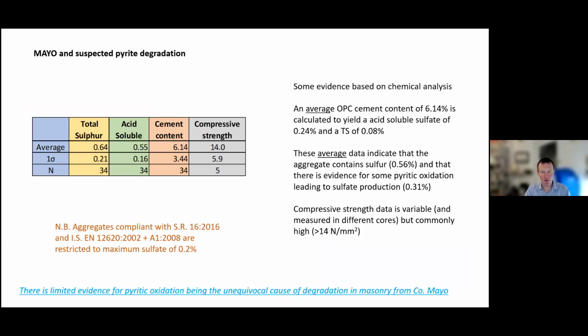So if we return to the notion of the cement content and we accept that the data is valid, it will allow us to effectively subtract the amount of sulfur that the cement would have contributed to the concrete block. And then we can look at the total sulfur and the acid soluble sulfate with the cement removed, because cement includes sulfur. So if we do that, what we can see is that there is some evidence for oxidation of pyrite based on sulfate production. We're not seeing it in the thin section or the SEM, but we are seeing it chemically. So it's a little bit of a puzzle and needs some more work.